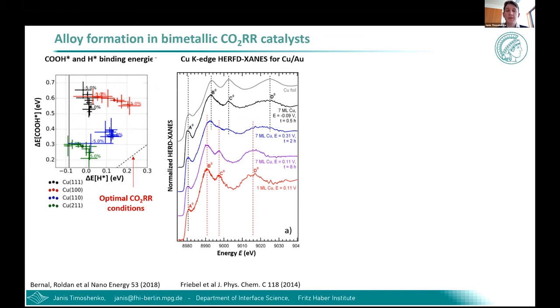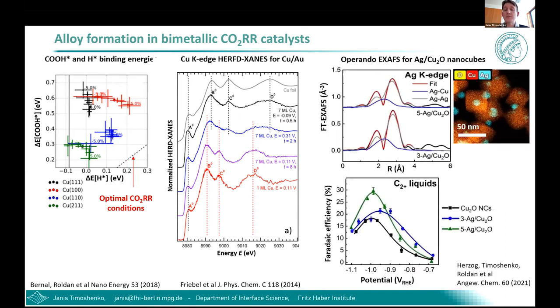But interatomic distances are also not the whole picture. In some cases, for example, for the silver-copper system, what's important to see is just whether there are neighboring copper and silver atoms in the system, because these copper and silver proximity effects are believed to be quite important for CO2 conversion again to these multi-carbon products.